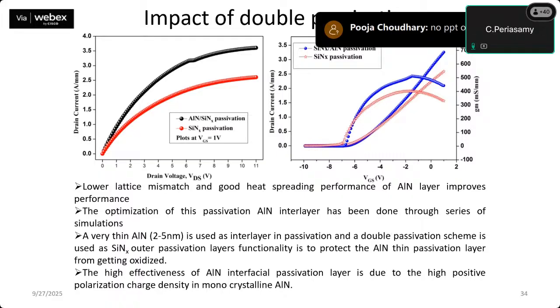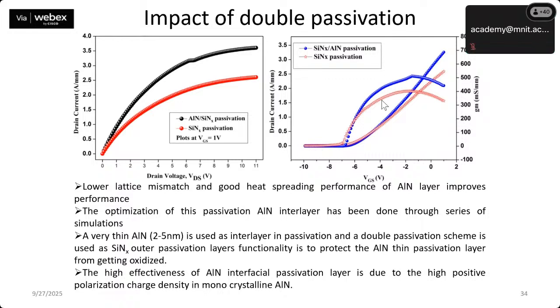Okay, thank you. So we have used different passivation layers to study the effect on the output characteristics of this proposed structure, particularly the drain current. From this result one can easily observe that after introducing the passivation layer on the proposed structure, the drain current is drastically increased, and the optimized passivation layer thickness is 2 to 5 nanometers. This is the optimized parameter detail.